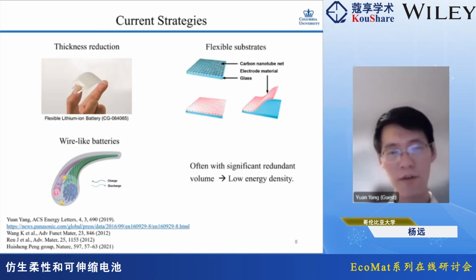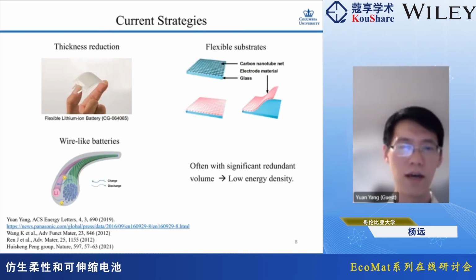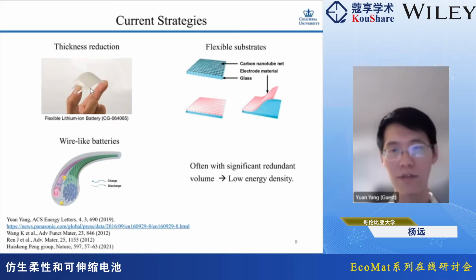To solve these problems, there are several strategies. For example, we can reduce the thickness, which is very straightforward. You have thin cells, and then the strain inside will be lower. But because batteries always have a package, if you have, for example, just one layer of the active material inside, the energy density will be reduced a lot. Also, for example, people use carbon-based materials as a flexible substrate. That can solve the problem partially. Carbon materials often have low conductivity and also add weight.